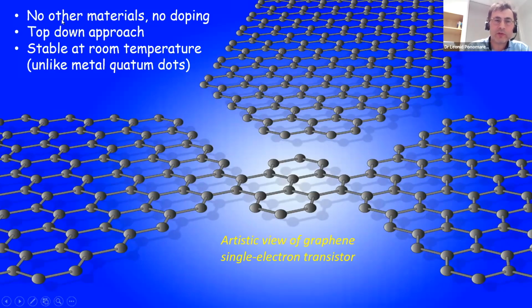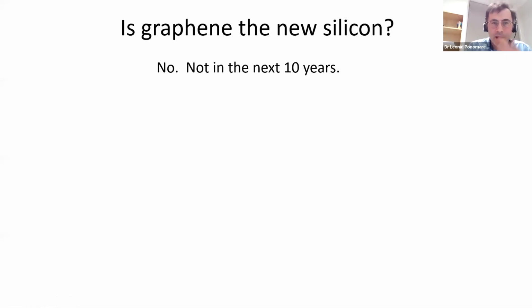But what is really important here is that the bonds between carbon atoms in graphene are so strong that this structure will be stable at room temperature, even if we apply some reasonable currents. If we try to make a similar structure out of anything else, like metal, it will simply not work, because passing the current will knock these atoms from their positions, and this device will stop working. Okay, so I'm approaching the end of it.